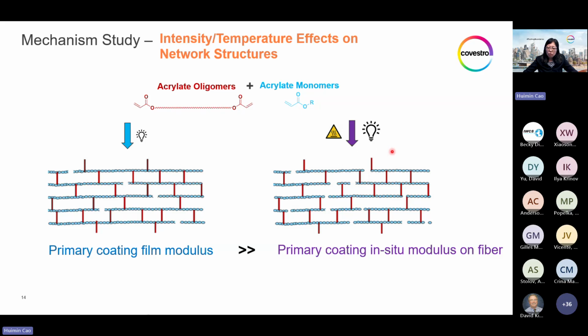condition, the free radical concentration increases, causing the termination rate to increase. And in the meantime, under high temperature, side reactions take place more. Both the high intensity and high temperature cause some chains to end earlier. So it will end up having many more network defects, chain ends, dangling chains, and the consequence of these network defects is the coating modulus on fiber is always lower than film modulus.